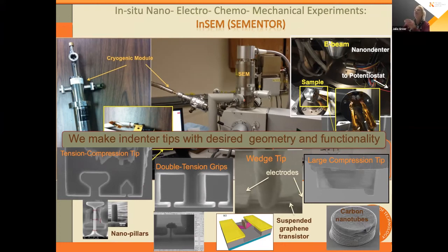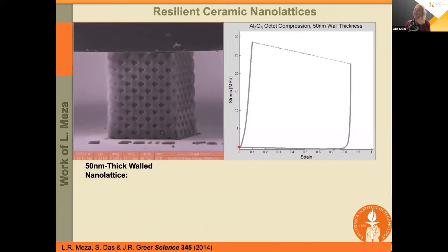So we're able to pull on them, we're able to deform them in a variety of different ways. And what I'd like to share with you here is a video of one of these nano-architected materials where the wall thickness of each individual beam is on the order of 50 nanometers. Now, this is alumina. This is a very brittle material. And so, of course, it's effectively your coffee mug with a severe case of osteoporosis.